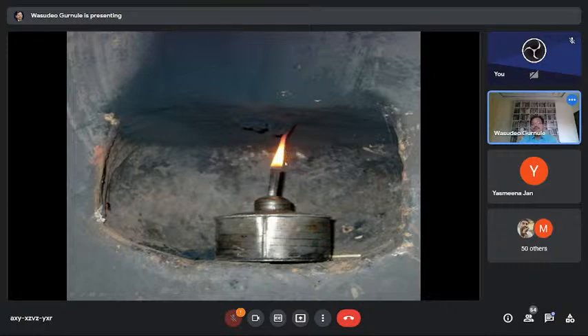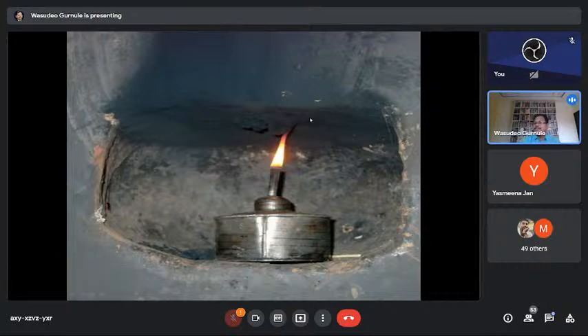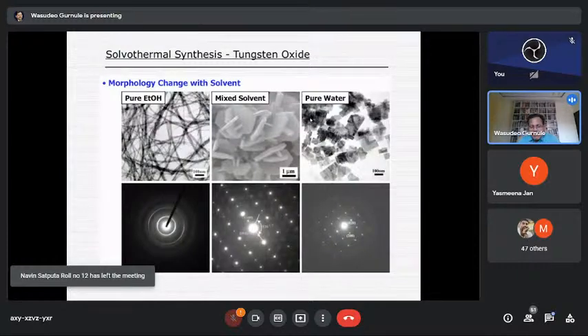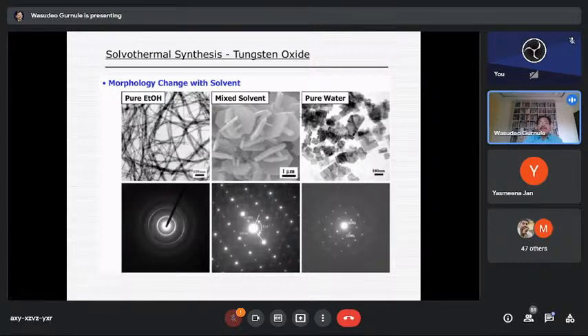We have to fix the flame in this way. Because of this, there is not complete combustion, but incomplete combustion. The carbon gets collected on the wall of the window like that, and when we analyze it, it is found to be nano size. So nanomaterials can also be synthesized by using the slow combustion process. This is the morphology, one figure is shown here. As we change the solvent, the nature or morphology of the material also changes. Tungsten oxide is shown here in pure ethanol, in mixed solvent, and here in pure water. So see, the nature, or we can say the morphology, is different for the same compound.